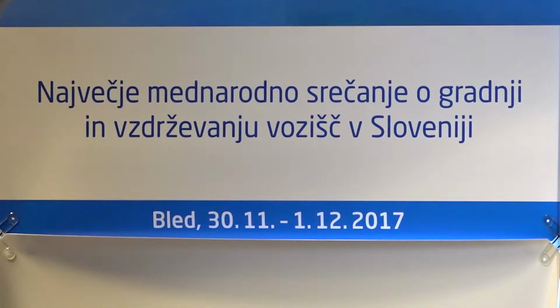So we have our boxes with the two key parameters, and we can now discriminate among the different binders very well. The pity is that the boxes show overlapping. That is because our binder characterization is not very well worked out yet. If you buy, let's say, a 5070, the rheological properties of this 5070 could be very similar to a 3045 within the overlapping area. With this method, it's the first time we can clearly distinguish where our bitumen is. So very nice.